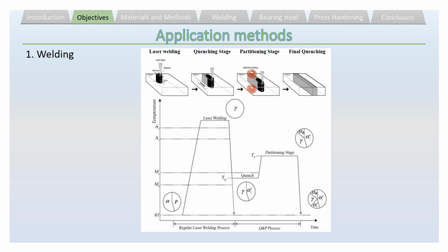So we have some martensite, and after that we increase the temperature by heating the sample again, but for a very, very short time. Depending on chemical composition, it could be just a few seconds or a maximum of a few minutes. So at the end, we have tempered the martensite formed during the first quenching, and we have some stabilized austenite. That's very interesting, because we normally need to do post-welding heat treatment after laser welding, and depending on chemical composition, it could take between 5 to 30 minutes.